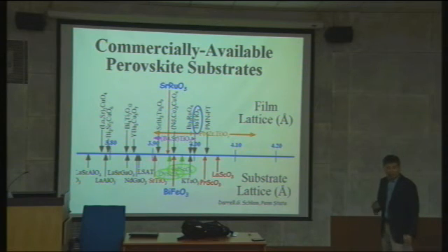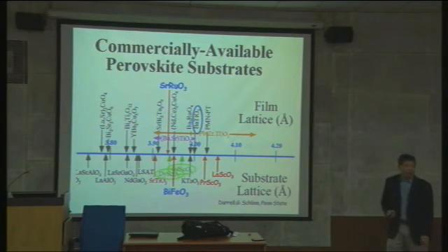So now, the largest substrate is the praseodymium scandate, and people are trying to make this region too, because some of those materials need a larger lattice mismatch, like barium bismuth oxide superconductor, or barium stannate, which is a high electron mobility transparent conductor. Those are in this range, and you don't have a substrate really matching this, so you have to make a new substrate. That's what some other researchers are trying to do, make a new single crystal substrate in that region.